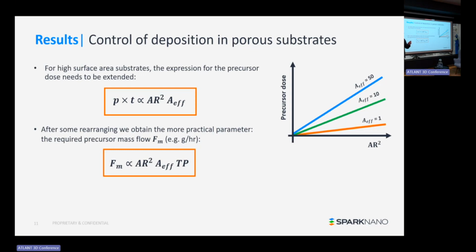If you optimize your ALD process on a 1 by 1 square centimeter chip matrix device and you come up with a certain precursor dose to conformally coat a certain aspect ratio, and you then expect to use the same dose on a high pore density substrate wafer, a DRAM wafer, whatever, that will not work. So you have to think a bit bigger than that.